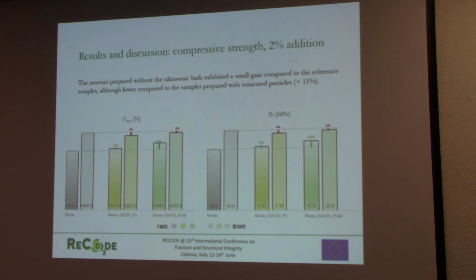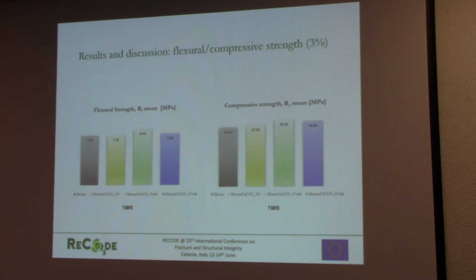Regarding the compressive strength, the trend is absolutely similar to the previous one, but in this case we noted that the mortar prepared without the ultrasonic bath exhibits a small gain compared to the reference one. As I said before, we are now investigating other percentages. In this case, with the percentage of 3% with respect to the weight of cement, we noticed that both for flexural strength and compressive strength, there is a small decrease with respect to the same composition, but with the 2% of nanoparticles of calcium carbonate.